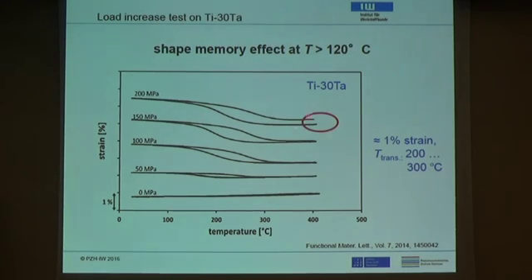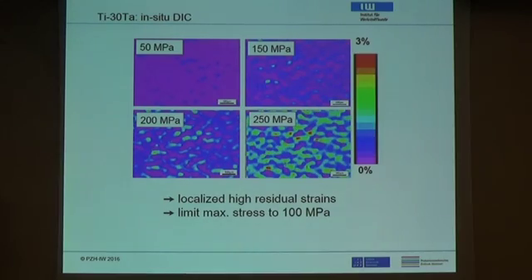The problem is shown up here. If you go to 200 MPa, then the loops do not close anymore, and you have some residual strain there. In the next step, we did some digital image correlation in situ in these experiments. What you see here is the strain field upon unloading for 50 MPa. There's basically no strain, but for the high stresses, you see these islands popping up with fairly large local strains of the order of 3% or so, which means there's a lot of plasticity going on.